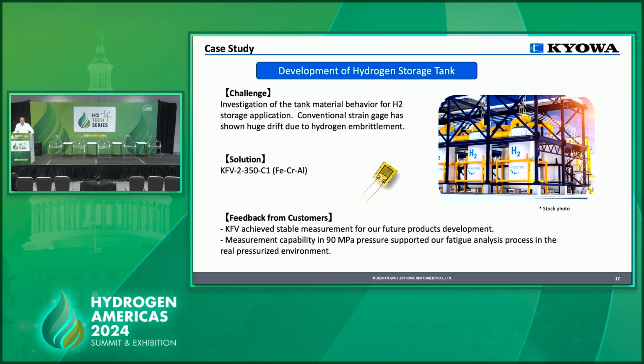Because of the superior performance of KFV strain gauges, this KFV solution has been used for development of hydrogen storage tank material analysis and also transmission pipeline material analysis. One example is an investigation of tank material behavior for H2 storage application. Conventional strain gauges on the market showed significant drifting due to hydrogen embrittlement, so they couldn't do accurate strain measurement. So they switched to KFV strain gauges made of iron chromium alloy, and they could achieve more stable and accurate measurement for their future product development. Also, measurement capability in the 90 megapascal high pressure range supported their fatigue analysis process in their real pressurized environment.